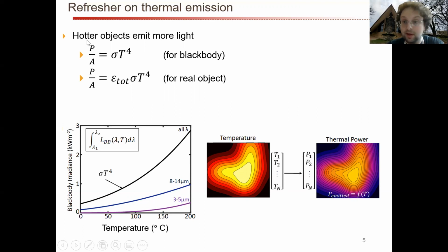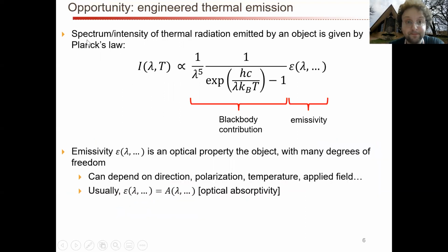This is essentially the one-to-one map up here. So there's an opportunity here, which is to engineer thermal emission for a wide variety of applications. The spectrum and intensity of thermal radiation emitted by an object is this Planck law multiplied by this emissivity, which is between 0 and 1, and it can be a function of many, many things. It can be a function of wavelength, direction, polarization, temperature, applied field, and so forth. So you can really use that to engineer the emissivity.